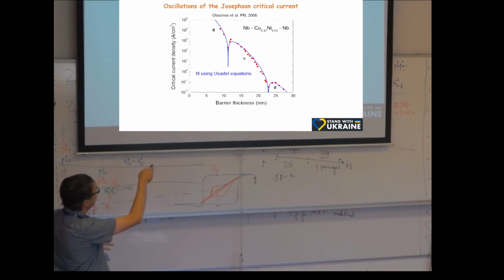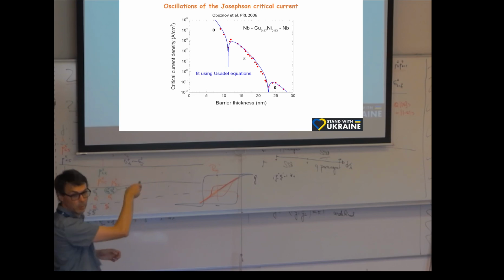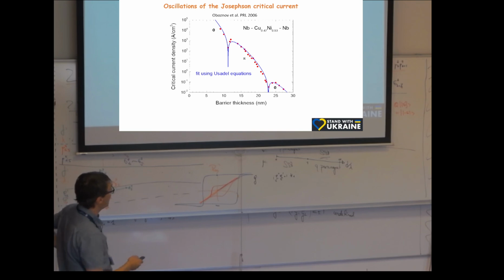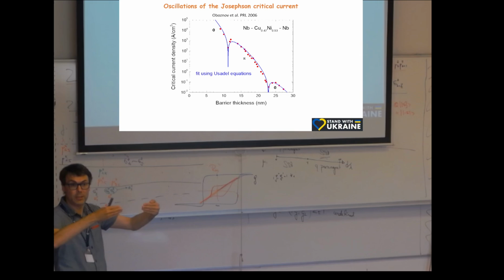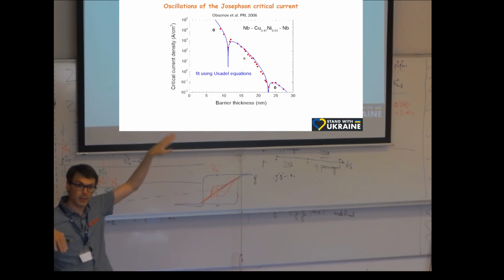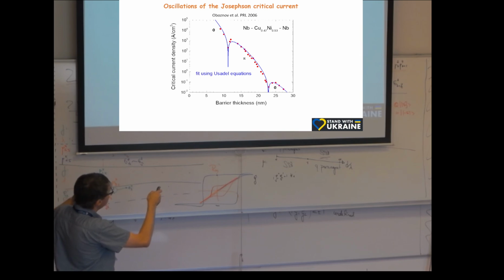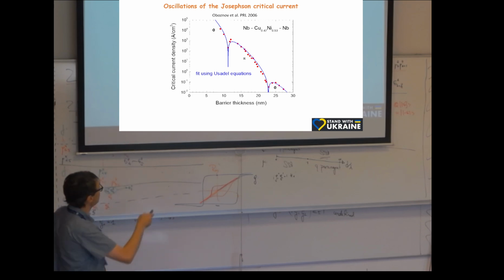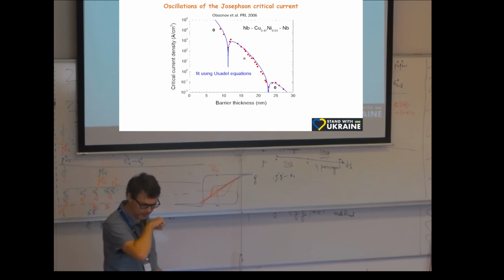So you see it, first of all, that it decays. And this is a logarithmic plot. So it's a pretty fast decay of the signal. And that's the overall decay. As you put the two superconductors farther apart, the thing decays. Now, in addition to decay, there are special points where it goes to zero, essentially, because this is, again, a logarithmic plot. And so the idea is that this is 0, this is pi, this is 0. So 1.5 periods of oscillation they were able to map out.